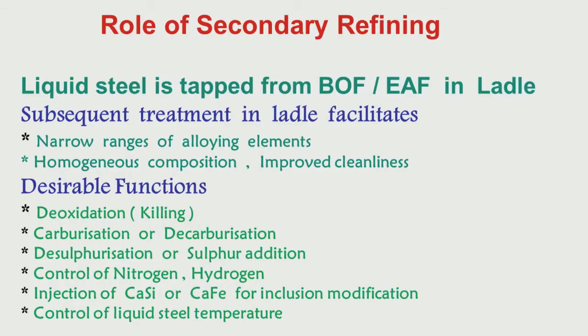Now, I have also covered what is the role, what is expected in the secondary refining stages. First, liquid steel is tapped from the basic oxygen furnace or electric arc furnace into a ladle. So for the subsequent treatment in the ladle, what is expected? We should get narrow ranges of alloying elements. We should get a homogeneous composition as well as homogeneous temperature throughout the liquid steel. But we must get improved cleanliness. That is the principal requirement for secondary refining.